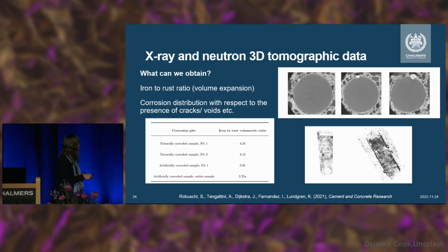But what we also did was to try to evaluate it for the whole sample from the artificially corroded one. And then it's about 2. That's interesting, because that is what most people have been using in analysis. But what we need to consider is that that is not the free expansion. That is the expansion that it managed to create because it was compressed back by the concrete. So how to express this in modeling is not completely straightforward, I would say. But I think that the free volume expansion is something we'd rather want, and want to know the mechanical behavior of the corrosion as such.